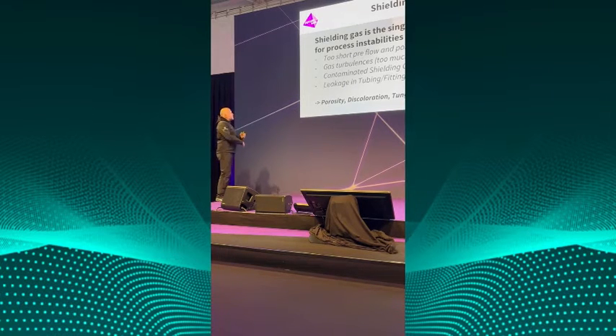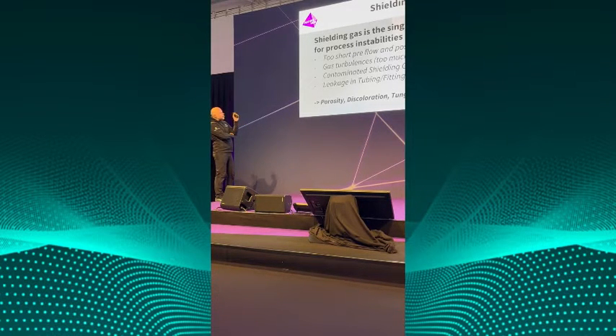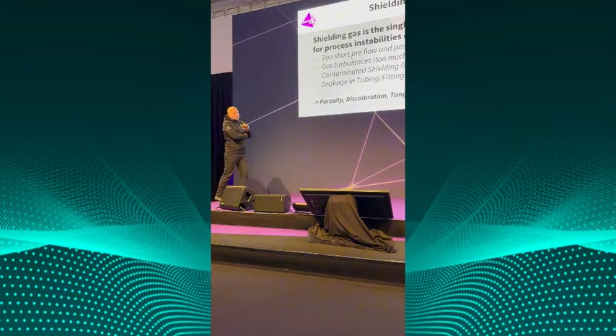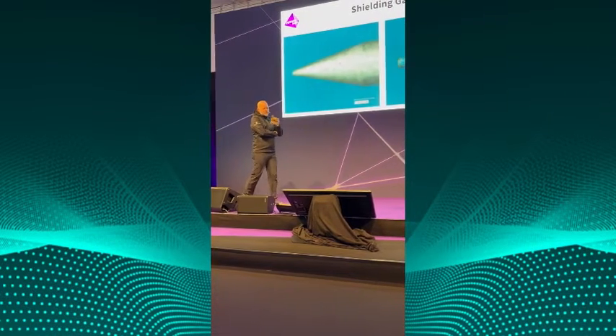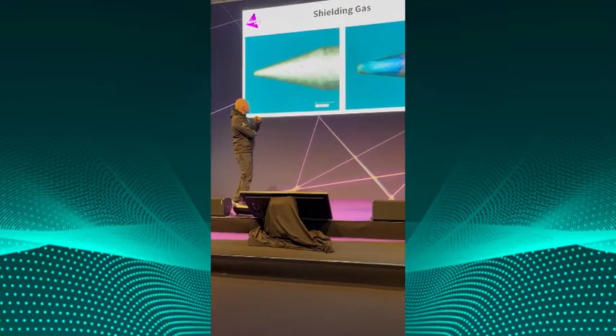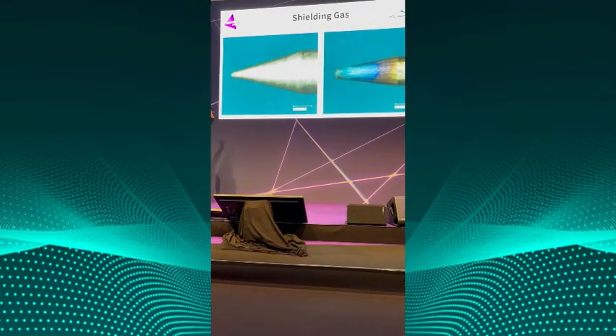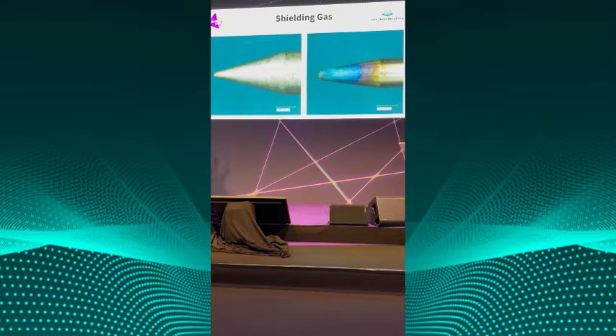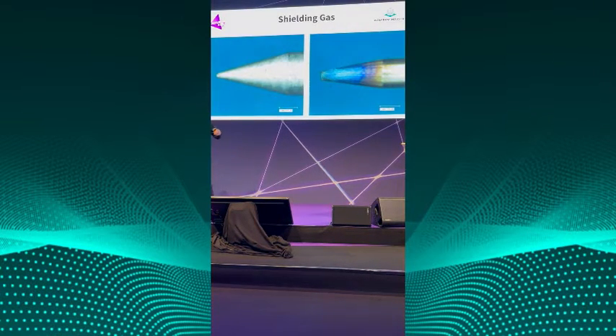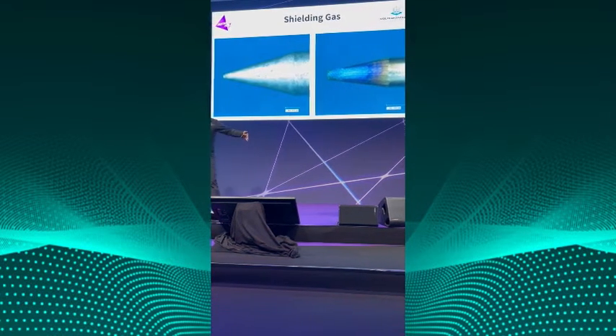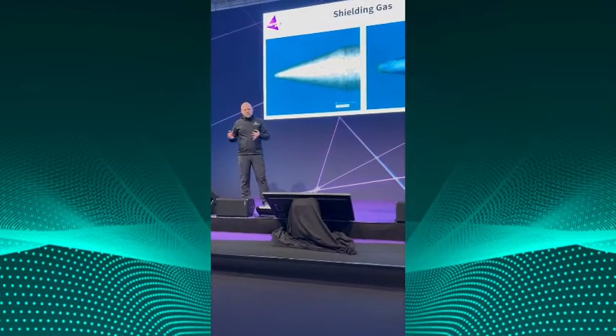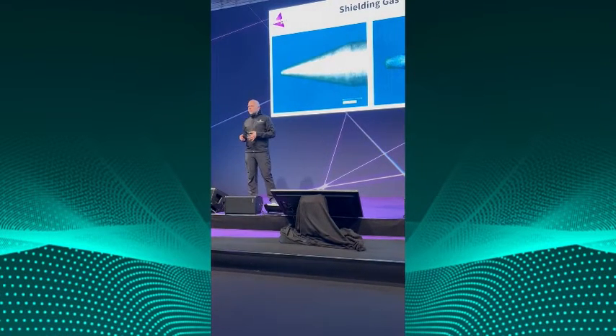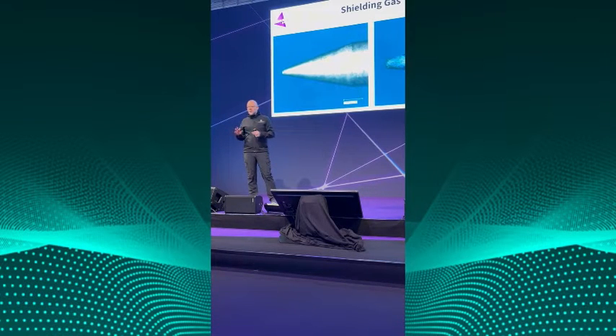So porosity, discoloration, tungsten wear, and arc instabilities are linked to problems with the shielding gas. Some pictures of tungsten electrodes. On the left side, there's a tungsten electrode which has too little pre-flow time. If you have a 6-meter torch hose, and on Monday morning you have 0.2 seconds of pre-flow time, you will burn your tungsten in plain air before it even started the new week.